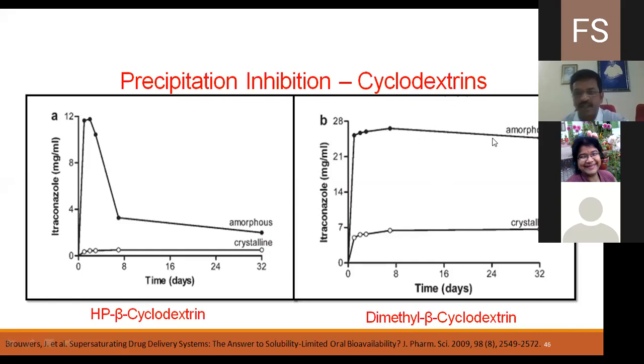You can see here, this is the drug itraconazole with dimethyl beta cyclodextrin, and its spring level is good and parachute level is also good. But when you compare the two, spring level is good with HP beta cyclodextrin, very similar to dimethyl beta cyclodextrin. But parachute effect is not that good with HP beta cyclodextrin, but is good with dimethyl beta cyclodextrin. So for itraconazole, this is the cyclodextrin that can better act as precipitation inhibitor.